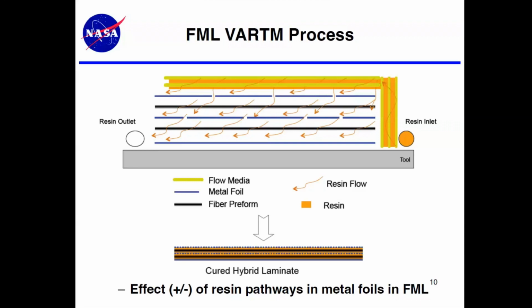What we've done essentially is we've inserted small holes, we'll call them resin pathways, into the metal foils. The resin flows through the flow media and then through the thickness, through the holes in the metal foils, wetting out the preforms and then subsequent layers below. When the part is fully infused, the resin pot is closed, the vacuum is closed, and then it's cured just by a standard oven process.